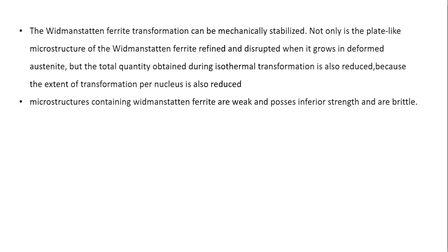Microstructures containing Widmanstatten ferrite are weak and possess inferior strength and are brittle. So, apart from the academic interest, particularly of displacive transformations, the microstructures of Widmanstatten ferrite are not suitable for practical applications because of the brittleness this particular transformation imposes to the mechanical properties of the steel.